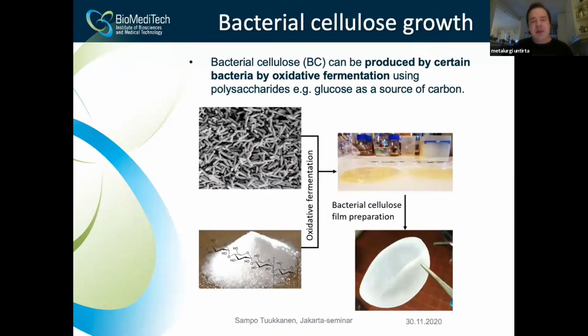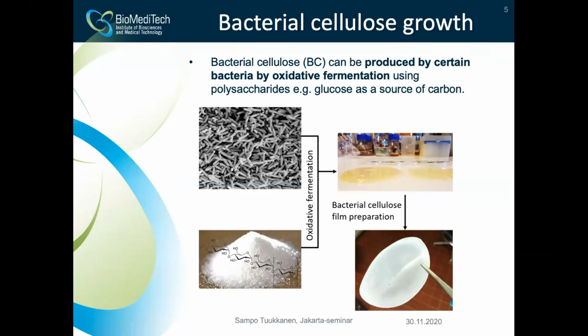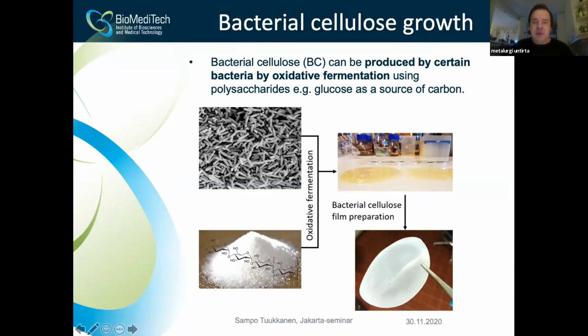Then we have also studied another approach, because there are some bacteria. There's another way to produce nanocellulose material films. Some bacteria produce cellulose using polysaccharides as a source material, normally glucose. Here I have this in a picture. We put some sugar in, and with fermentation they produce film-type structures. When you dry these films, you can prepare freestanding nanocellulose films.